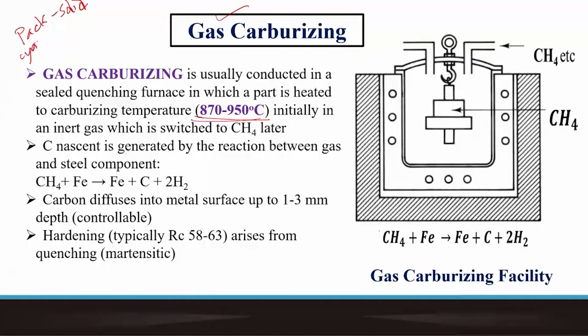and in the gaseous state we are dealing with a slightly different charge, again primarily methane as the primary source of carbon, and here this is the overall reaction, but release of carbon doesn't happen directly from methane. It goes through a certain decomposition process, but the overall reaction would look somewhat like this. And it is this carbon which comes out in the nascent form and gets adsorbed, diffused and dissolved at the